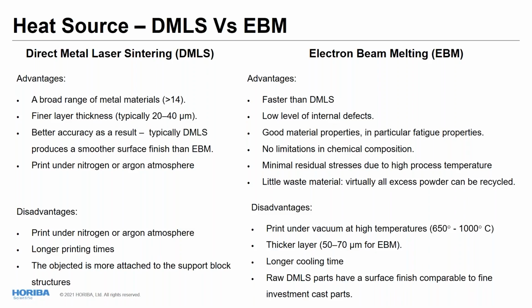Usually you expect better surface results when you use laser, but also longer printing times, because the laser does one point at a time, and with electron beams you have multiple beams simultaneously printing the particles. So your printing time in that sense will be faster. But with electron beam, you are also required to use very high temperatures, from 650 or sometimes up to 1,000 degrees Celsius, which means it takes time to heat up the system, a lot of energy consumption to keep your printing chamber at that temperature, and you also have to wait for the printed parts to cool down until you're able to remove them.